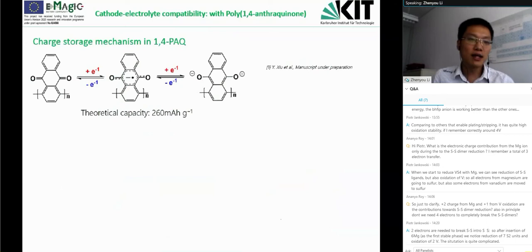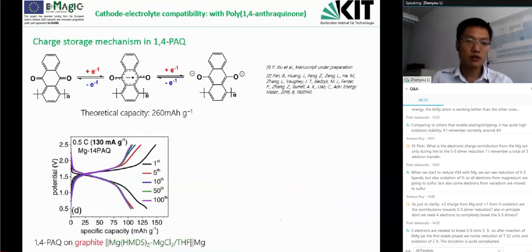So basically the charge storage mechanism of this PAQ material relies on the redox of these carbonyl groups. And if we consider both carbonyl groups involved in the reaction, we have a theoretic capacity of 260. But in the practical case, as reported previously, the accessible capacity is only around 110, which is only less than half of the theoretic value.